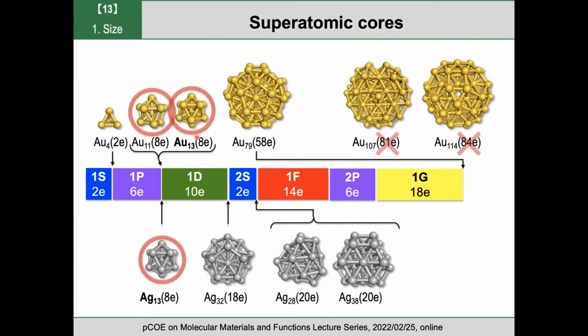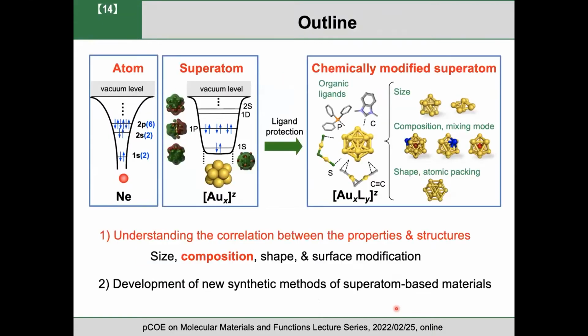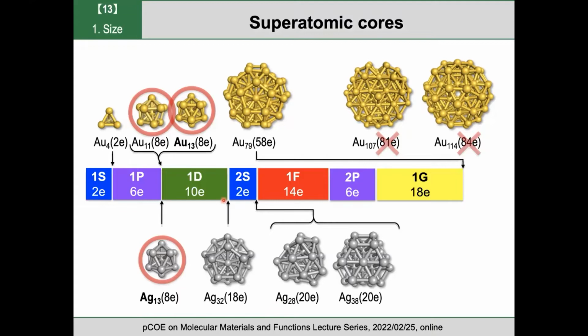So here are the structures of the gold core and the silver core reported so far. And when we count the number of electrons for these cores, these smaller clusters can be explained by the electronic shell closure. But for these clusters, the numbers of electrons are 81 and 84. These numbers are not good for electron counting. So for clusters smaller than this region, the electron counting is important. But for the larger clusters, maybe the geometrical packing is a key parameter of the stability. And in the case of silver clusters, these smaller clusters satisfy the electronic shell closure. So the message is that for these smaller gold and silver clusters, the electronic shell closure is important.